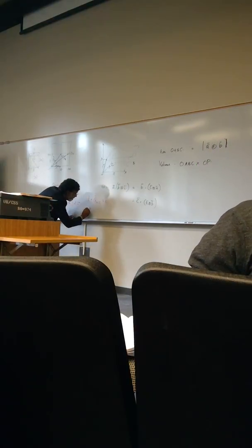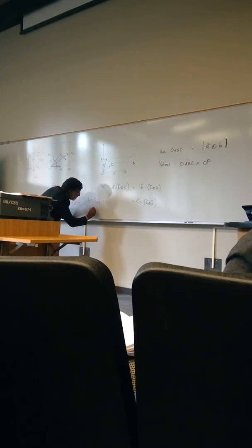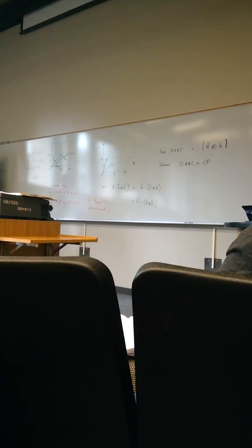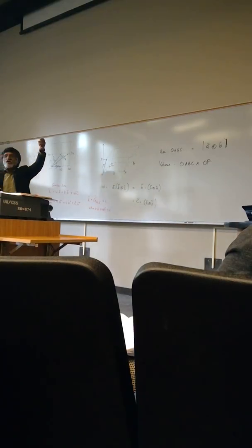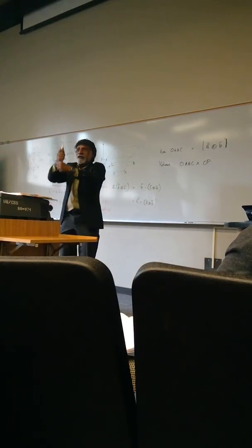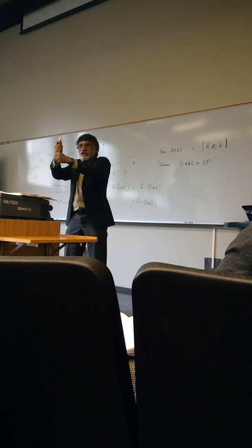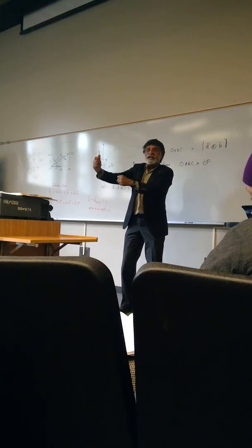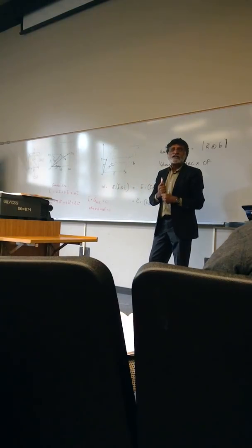So UH plus VK plus WL equals 0. This is the rule for that zone axis pattern that I showed you in the diffraction. You have a specific vector here, the direction, and in all the diffraction patterns, all the planes are always perpendicular to this in that particular zone.